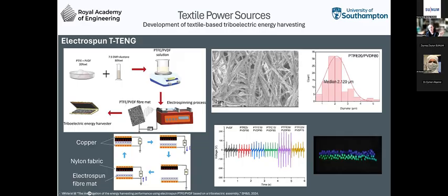And what we've done is take PVDF, which is a standard negative triboelectric material, and enhance its performance by adding PTFE, which is even more negative as a triboelectric material. We've optimized the blend, so 20% PTFE to 80% PVDF by weight, and that produces the clearest increase in voltage output. You can see here in the bottom left the mode of operation of this particular example.